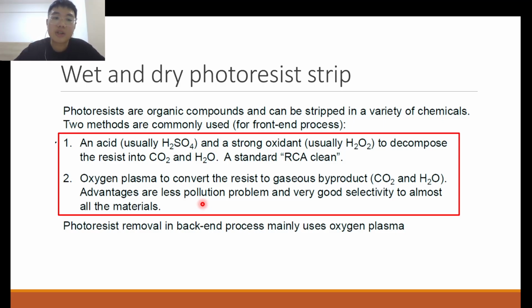It turns out that we can use either of these, but sometimes we have certain cases where we prefer one over the other. For example, for photoresist removal in back-end processes, you may want to use more of the oxygen plasma, especially if your metal interconnects are exposed. This is because in the back-end process, you already have a lot of the metal interconnects, your copper interconnects, for example. Nowadays, you mostly use copper.